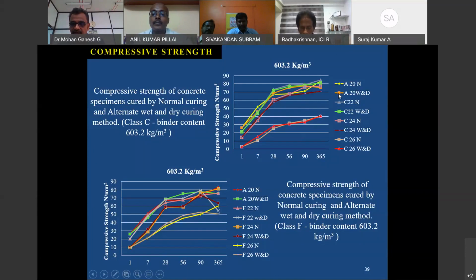Wet and dry. This is a 60% replacement. Normal curing and alternate wet and dry curing with class C fly ash. A small minute difference is there in the beginning days, but later both are comparable. At either 365 days or 56 or 90 days, we are getting nearly the same strength. With class F fly ash also the same. This is for 60% replacement with normal curing, and this is alternate wet and dry curing.